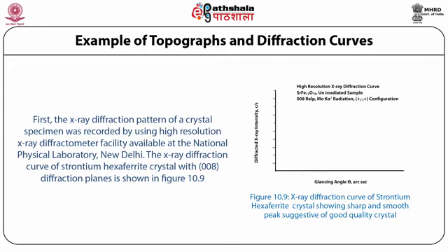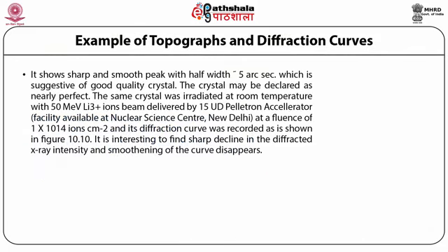It shows sharp and smooth peak with half width 5 arc second, which is suggestive of good quality crystal. The crystal may be declared as nearly perfect.